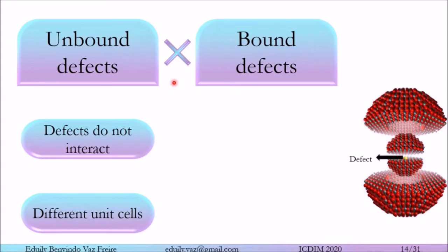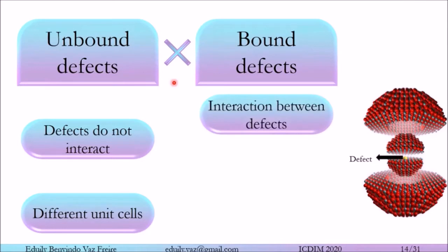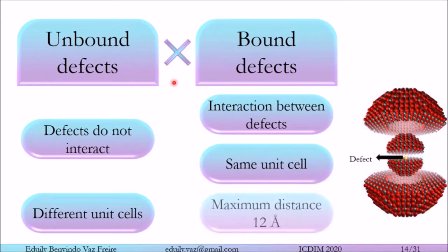And we have the bound defects, where the ions that form the defect can interact. They are usually in the same unit cell or in neighboring unit cells. However, the maximum distance for a defect to be called bound is 12 angstroms, precisely because our short-range potentials have a maximum range of 12 angstroms.